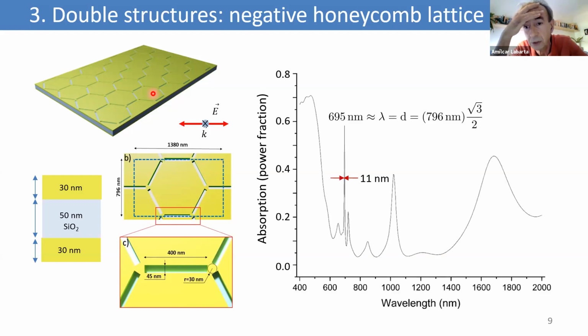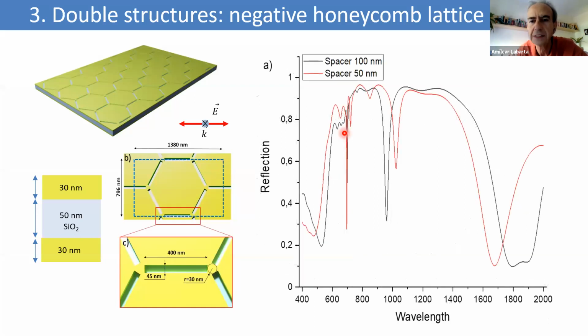Okay, here the absorption of this system. Look at this very sharp and narrow peak of only 11 nanometers corresponding to the collective excitation. It is very well defined, so it could be useful for applications such as detection of changes in the surroundings of this structure, for instance, because you are changing the refractive index of the medium around it. The reflectivity shows an intense dip at the position of this absorption peak. So again, we can use the reflectivity to detect the presence of something in contact with the structure.